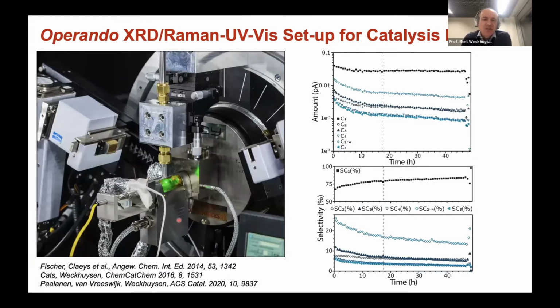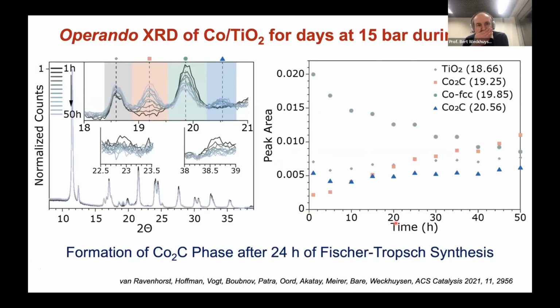And the first thing I want to discuss is not the X-ray spectroscopy, but the X-ray diffraction. In our lab at Utrecht University, we have a setup which allows you to do X-ray diffraction in the lab together with Raman, together with UV-Vis. This setup is operando, so you can also measure for this catalyst the conversion. And this should just convince you that you may not make just methane, but also higher hydrocarbons. If this catalyst is now put at the beamline at SLAC, and I'm still talking about the X-ray diffraction, if you now analyze the X-ray diffraction and you follow the different diffractograms or peaks, which are typical for carbide, metal, what you see is that you have here the formation of carbide.